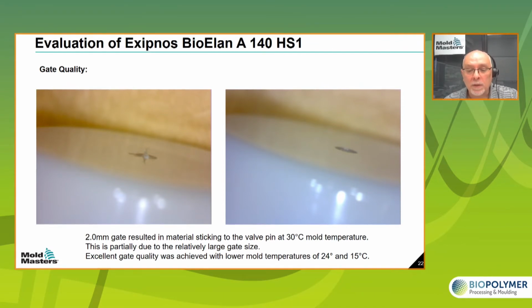When we go down in mold temperature and also in process temperature, we address that issue with the gate appearance. And on the right-hand side, you can see the result of that lower temperature, with 150 degree process temperature and 24 degree mold temperature. And we also assessed 15 degree mold temperature. And you can see that we achieved a quality gate appearance.